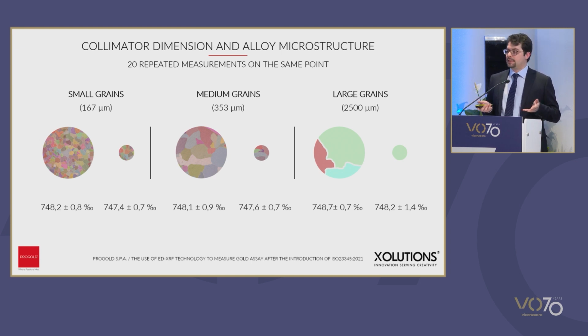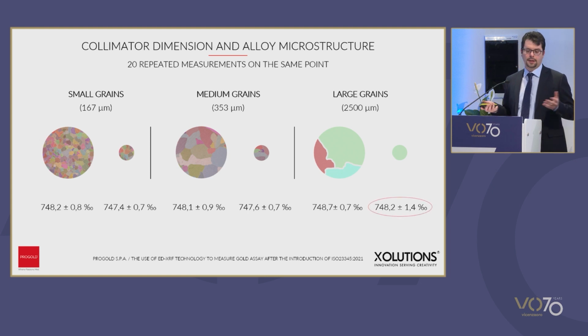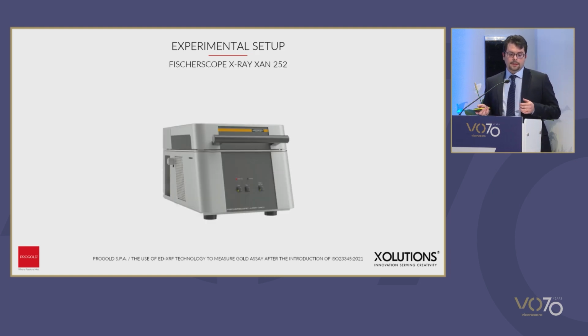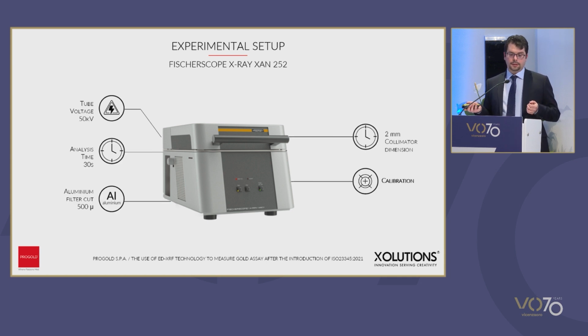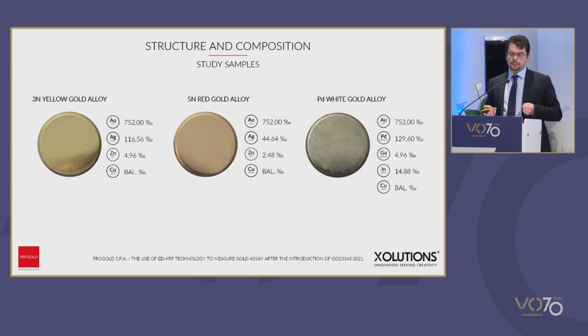Okay. Based on these results, we can conclude that it is better to use the biggest possible collimator, of course, if that is compatible with the sample. And we should pay attention, be particularly careful if our alloy has a large grain or inhomogeneous grains, because this can affect the analysis. Now, let's move to the second element that we have analyzed, that is the effect of calibration. We decided to have three different alloys, 3N yellow gold, 5N red gold alloy, and palladium white gold alloy.